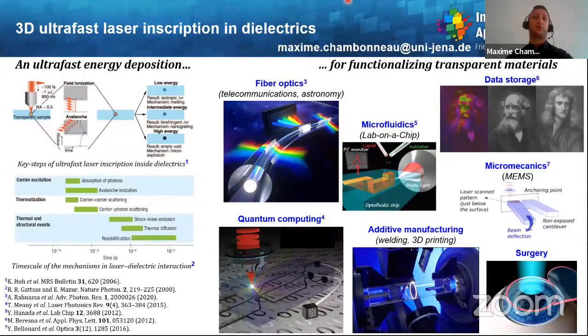ultrafast lasers represent an extraordinary tool for functionalizing dielectric materials, especially glasses, but also polymers. And the reason is contained here on the left, because at those ultrashort timescales, it is possible to first deliver energy to the electron subsystem, and then this energy will be released well after to the lattice. And this allows a clear separation between the causes, which are the energy deposition, from the consequences, which are the material response.